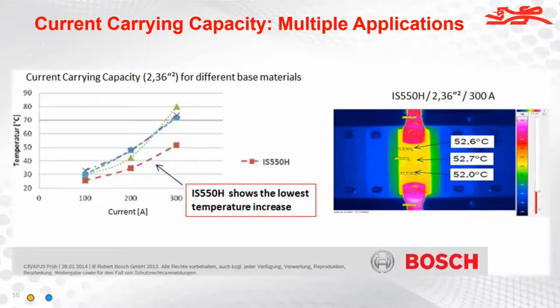You know, I've talked to some customers about going to thinner cores, so the ground plane can also help with the heat sinking away from the power plane. And I would think that this material would be a great option for that over FR4. Yeah, you're correct. The laminate's not a particularly good conductor of the thermal energy that is in the PCB, and so this material actually will move energy through the material much more rapidly into the copper, which is obviously much more thermally conductive. So you can get the energy and the heat out of that board. That heat and energy that is dwelling in a particular area, that's what's going to degrade the material and reduce the total lifetime capability of that particular PCB.